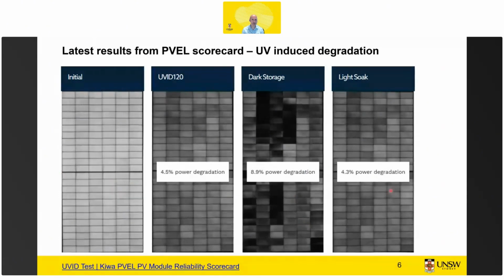So how do we see it? We see that actually modules are not uniform. We see this checkerboard pattern, particularly if you store the modules in the dark. And yeah, the degradation can be quite severe, and we see this dark storage degradation, and I will come back to that as well.